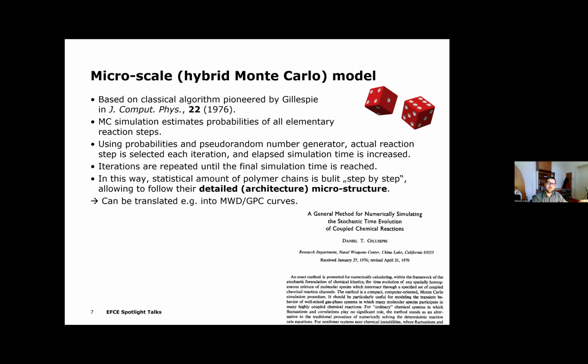particular iteration. So, for instance, at the beginning of the polymerization reaction, there is a high probability of propagation. So most of the time the propagation step is selected, while towards the later stages of the polymerization, we have a higher probability of transesterification or chain scission reactions. So this way, we actually build each of the polymer chains step by step, and that allows us to get the detailed information about their architecture, which can be later on translated into molecular weight distribution directly comparable to experimental data such as size exclusion chromatography or gel permeation chromatography curves.